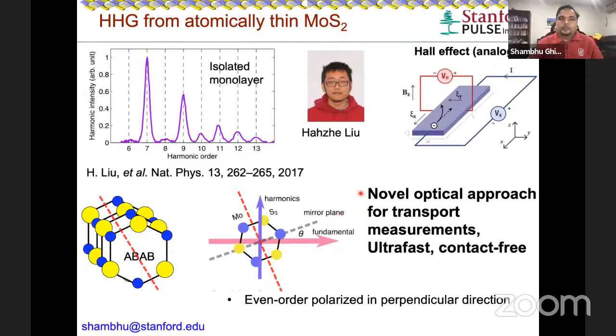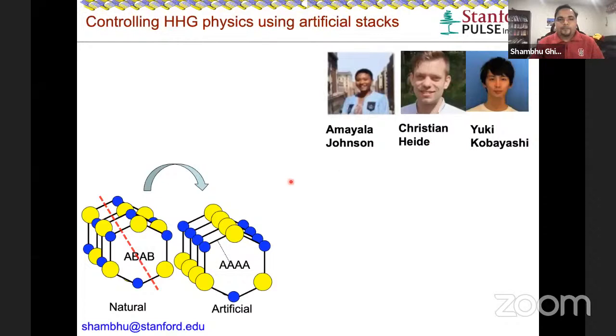What we did is we measured the polarization of these harmonics and found that even orders are polarized in the perpendicular direction, very similar to bismuth selenide, in reminiscence of the Hall effect. So this could be an all-optical approach, again, to probe the interesting physical properties of 2D systems. And recently, we have more people interested in this, students and postdocs in our groups, and they're doing wonderful work, actually taking this to a new level.